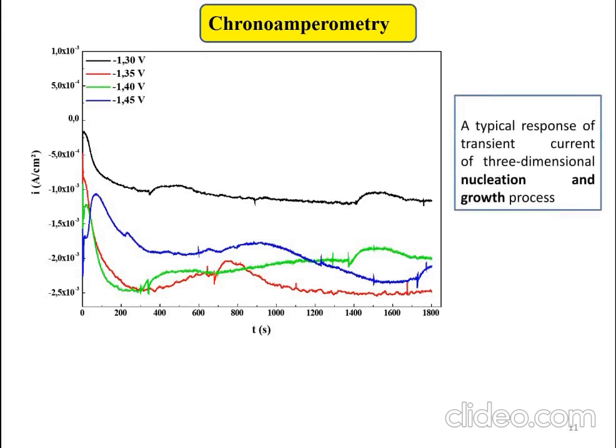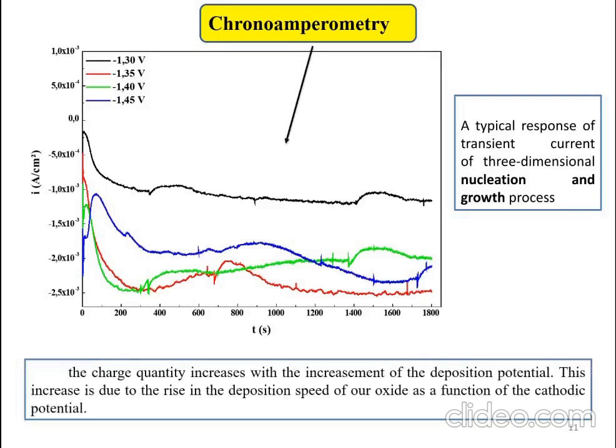The present curve shows a typical response of transient current of a three-dimensional nucleation and growth process. The charge quantity increases with the increase of the deposition potential. This increase is due to the rise in the deposition speed of our oxide as a function of the cathodic potential.